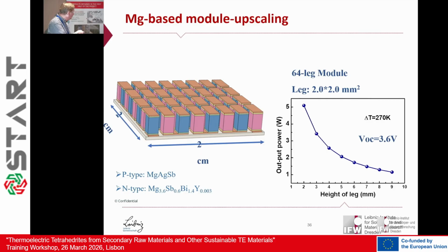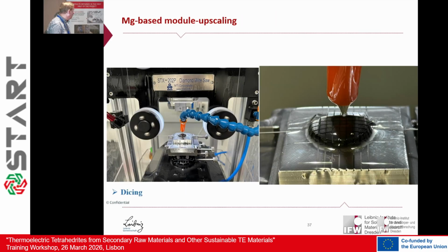The final module, this was a stage when we simulated the whole module, and this we are now fabricating on a larger scale. One of the challenges we figured out when we fabricated this material on a larger scale, also making modules out of it, was the dicing of this material. It takes, first of all, a lot of effort. There is also a cost analysis from Vicente Pacheco showing that the dicing process itself consumes a lot of money in the fabrication of the whole module. It's not really the material itself, but the dicing process.